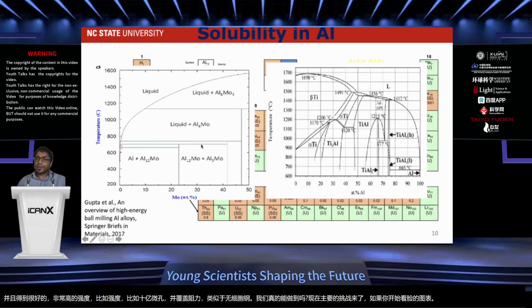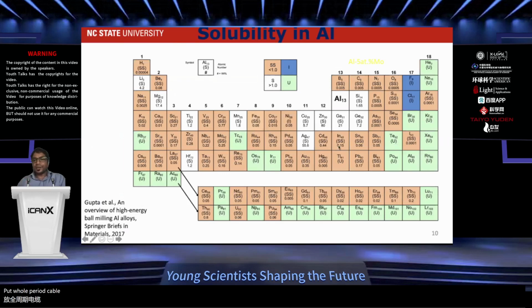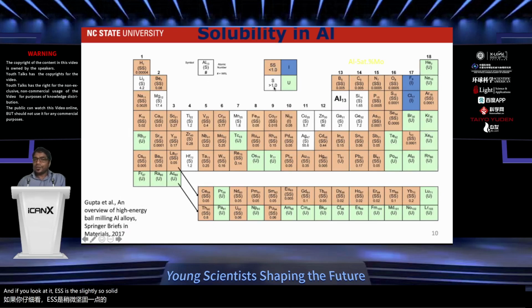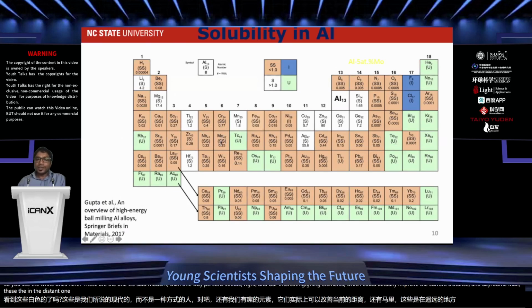Now, the main challenge comes if you start looking at the phase diagram. The solubility of most of the corrosion resistant elements in aluminum is very limited. So we put the whole periodic table together and looked at all these different elements and their solid solubility in aluminum. We color coded the periodic table: SS is slightly soluble, anything more than 1 weight percent is soluble, and the rest are unknown. The white ones are more than 1 weight percent soluble. Our interesting alloying elements which could improve the corrosion resistance, say chromium and moly, have very low solubility, and these values are the maximum.